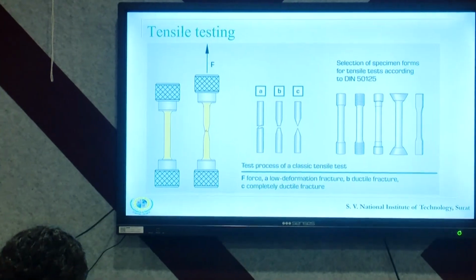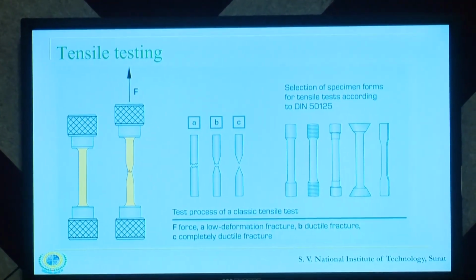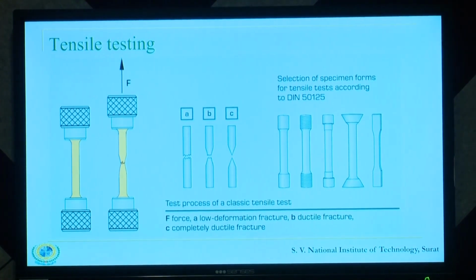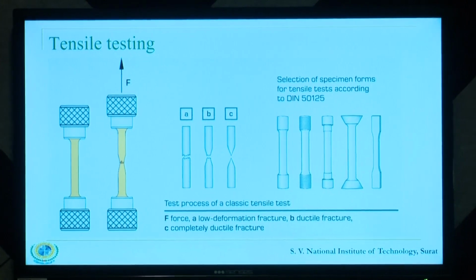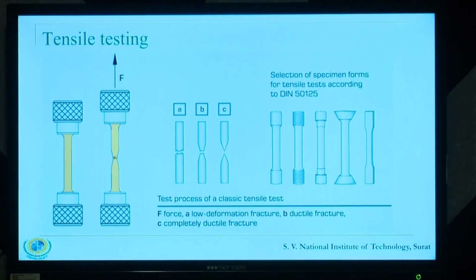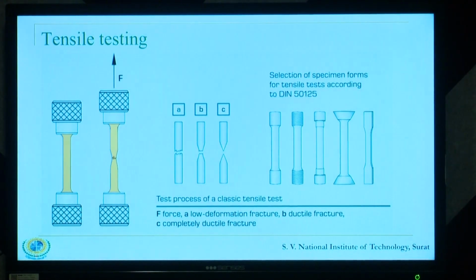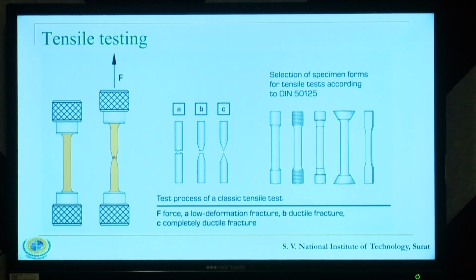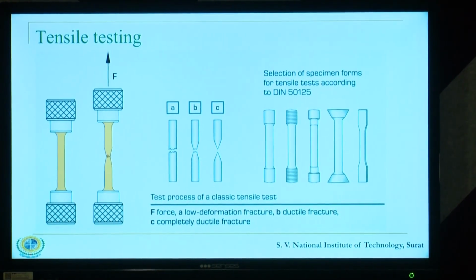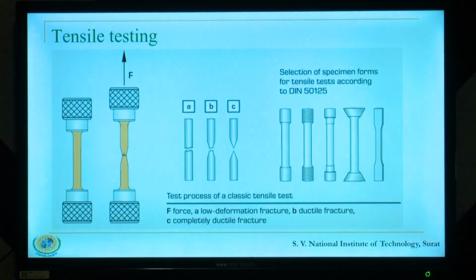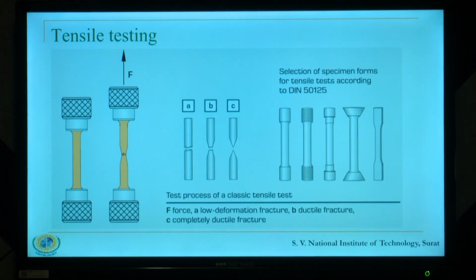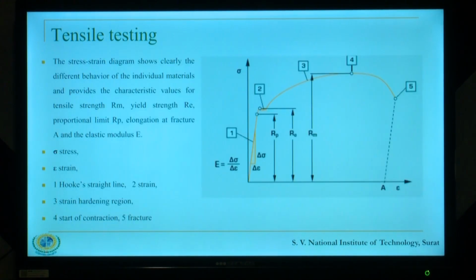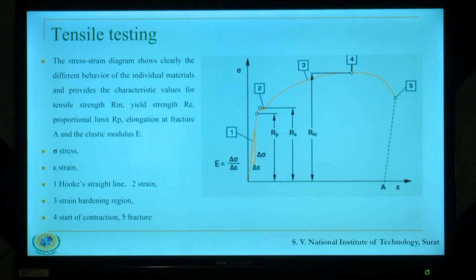Now, it is always interesting, and also known to us, that as per the standard there are different ways in which we can prepare the standard specimens. We will be able to select different shapes, different forms of standard specimen, and the way in which the fracture happens is usually in 3 ways. One is a deformation which leads to immediate failure. Sometimes you initiate the necking part and you see the failure. Sometimes necking is extended to a very high value and then we see the failure. In each of the cases we will see a separate type of stress strain curve, and that always is interesting to interpret. But in general this is the general stress strain curve that is being used.